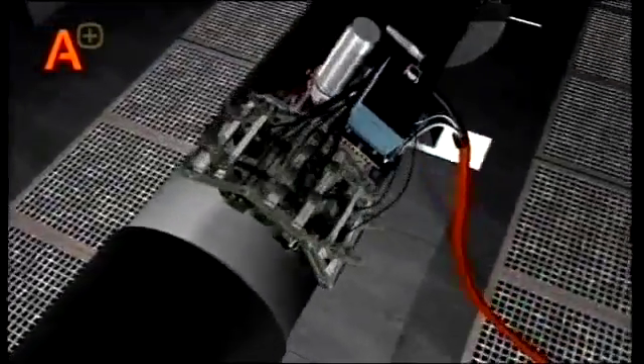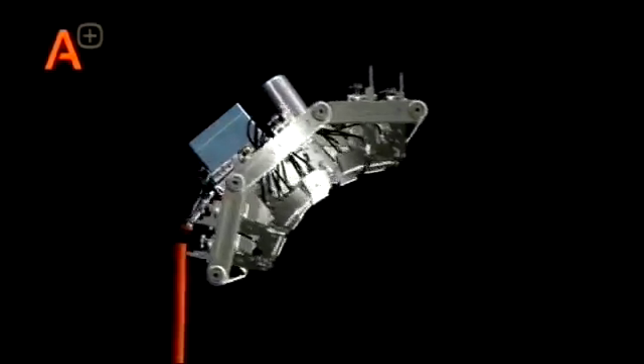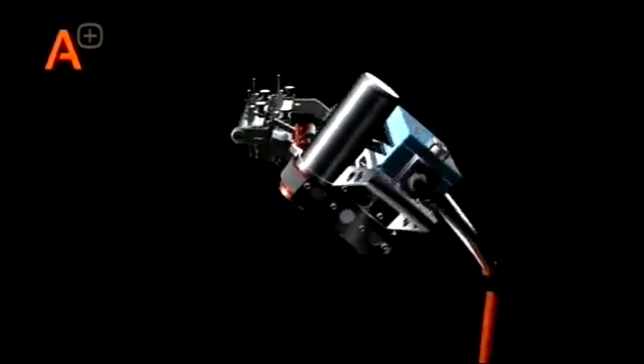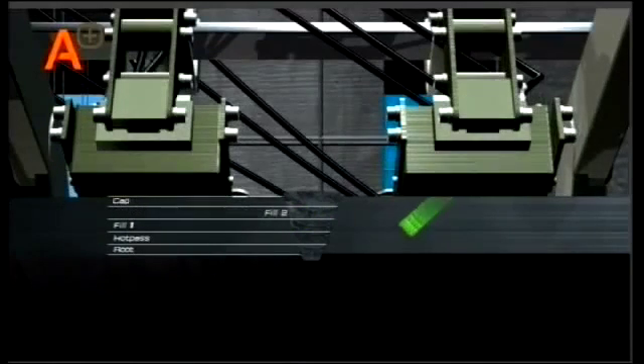The RotoScan inspection system makes use of ultrasound generated by ultrasonic transducers, each of which is dedicated to inspecting a specific part of the total weld volume. The first system transducer in the array employs a time-of-flight diffraction technique to look at the whole weld volume. Following inspection functions look at specific parts of the weld. This is possible because the transducers are made to produce a highly directional sound beam.